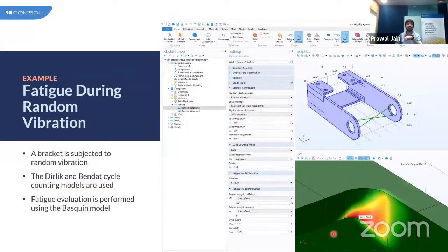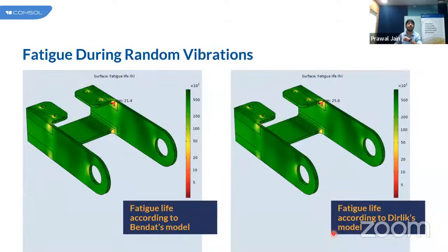In this case, again, we used the PSD data and got the fatigue life with different models, Bendat as well as Dirlik. We can see that both models predict a critical point near a stress concentration at the fillet. But Bendat's model predicts a shorter life than Dirlik's model. So in this case, Bendat's model tends to be conservative when the stress response is not a narrow band.